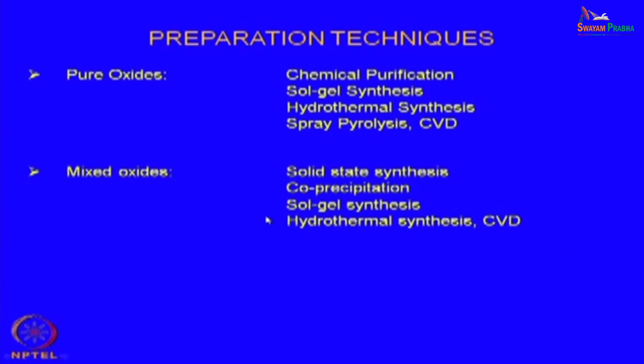So, they also have to be synthesized following special techniques. One very simple technique is what we call solid state sintering or solid state synthesis. If you want to make, for example, barium titanate, you just take barium oxide in the form of carbonate, barium carbonate, and then mix it with titanium dioxide and heat it to high temperature. At a high temperature there is a chemical reaction between barium oxide and titanium dioxide, and you get a second compound in the form of a mixed oxide called barium titanate.